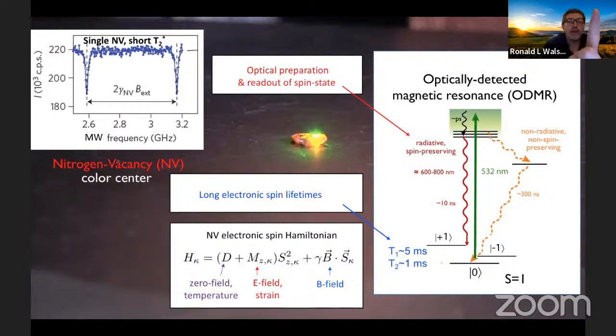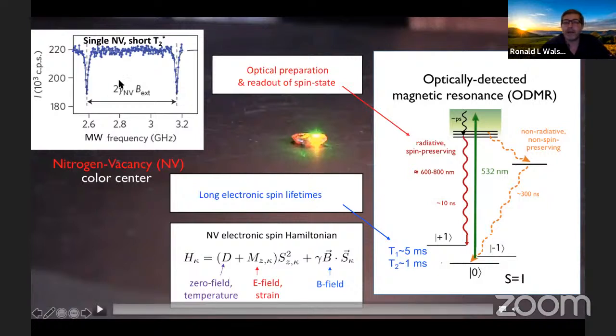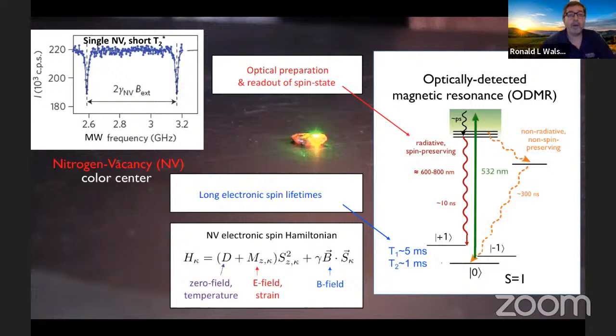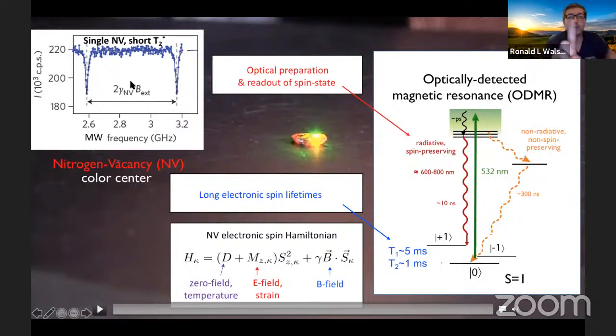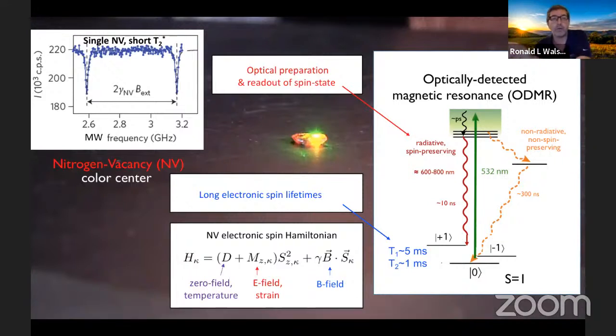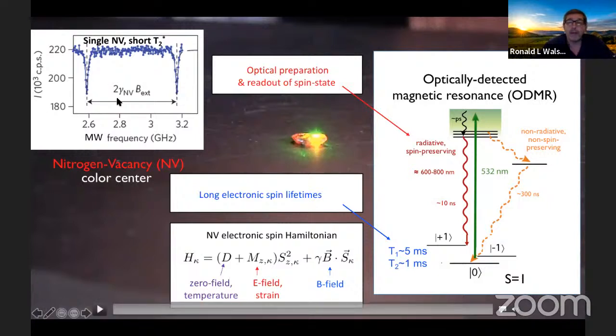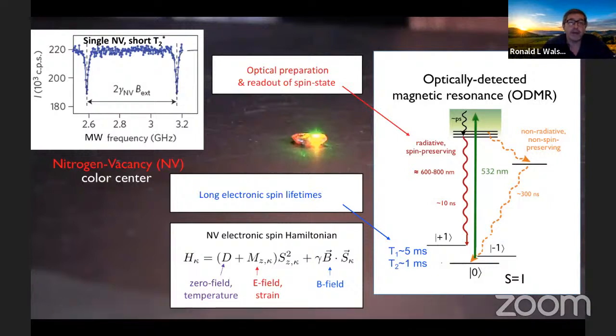Let me note that if you change that external field, these two peaks would shift. If you increase the field, they would split wider. If you decrease the magnetic field, they get closer. So you're really doing a spectroscopic measurement, and these sharp peaks give you the magnetic field. If you cared not about magnetic field, let's say about temperature, there would be a zero field splitting shift. And rather than the two lines shifting relative to each other, they'd both shift either to a higher frequency or to a lower microwave frequency. And so you could be able to do measurements of both temperature and magnetic field, for example.